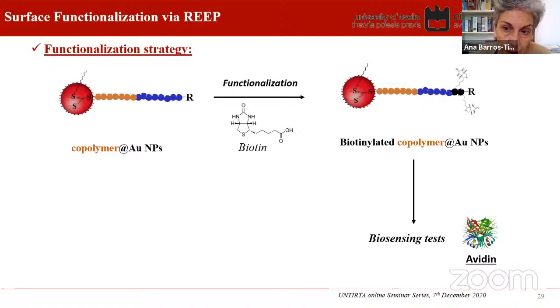So to do that, we had to anchor the biosensor bit, which in this case was biotin. So starting with the copolymer at the surface of the gold nanoparticles, we added actually a few repeating units that could react with the biotin to prepare biotinylated copolymer gold nanoparticles for the biosensing tests.